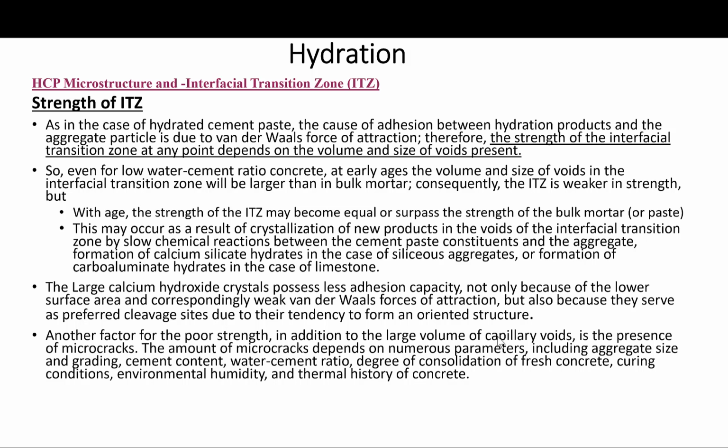For instance, a concrete mixture containing poorly graded aggregates is more prone to segregation during consolidation. So, thick water films can form around the coarse aggregate, especially beneath the particle. Under identical conditions, the larger the aggregate size, the thicker the water film. So the interfacial transition zone formed under these conditions will be susceptible to cracking when subjected to the influence of tensile stresses induced by differential movements between the aggregates and the hydrated cement paste, for example.